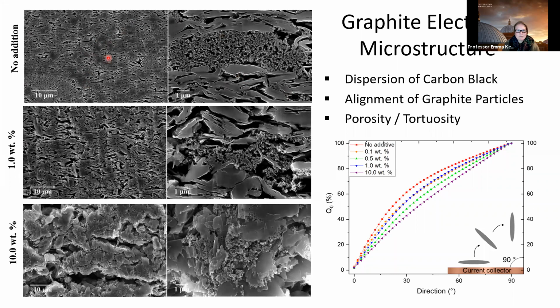And we could analyze what kind of angle our graphite was lying at from doing some digital analysis of these images. And this graph here just gives you an idea of whether it's lying flat or perpendicular. And if we look at the no additive here, you can see that the majority is less than 30 degrees in direction. So it's kind of like lying this way here. And as we added more secondary solvent in, we can actually change the microstructure and the alignment of the graphite flakes. And in this 1% here, you can see that we've got different pore sizes. We've got a slightly different distribution of our carbon black, and you can see that our graphite flakes are no longer just lying flat or perpendicular